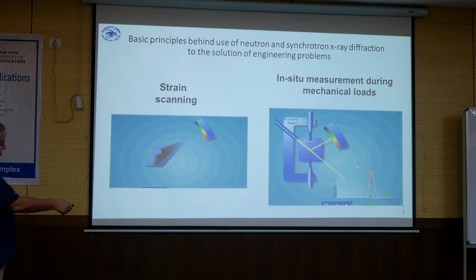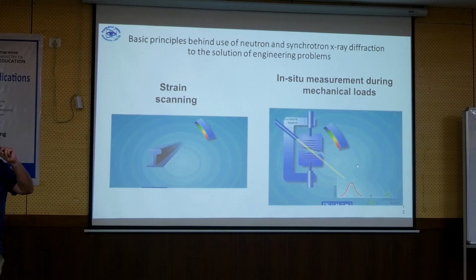So now it's in tension, so the peak shifts to the right because of the tensile stress. This is if you apply compression stress. Now you apply the tensile stress, it goes to the left. So it reacts to interplanar spacing. It is clear. And also you see here that the peak broadening is because you introduce defects and internal stresses. So we can follow the peak shift and peak broadening with the lattice defects.